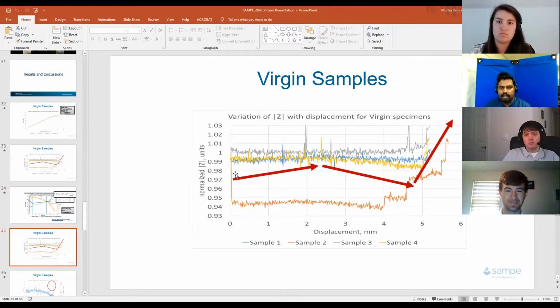But what we observed from my experiments was that we first had a small increase, then a decrease, and then an increase. What we thought was that we have used a unidirectional laminate in which all the layups are in the 0-degree direction. So when we saw the mechanical curve as well, it has a sudden failure. So we assume that will be one of the main reasons. And the literature data is all for impedance collected along the length of the material. But in our experiments, the impedance data was collected through the thickness of the material. So we assume these factors will make these variations.